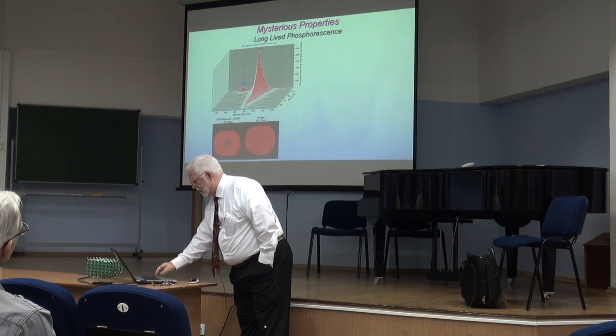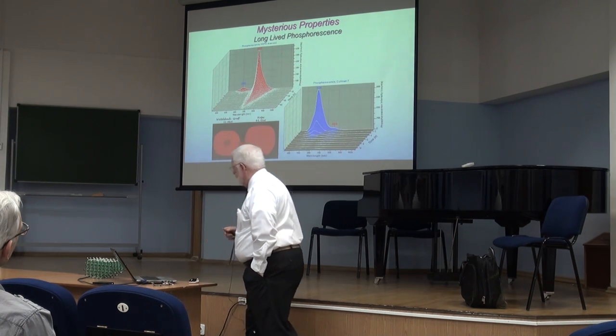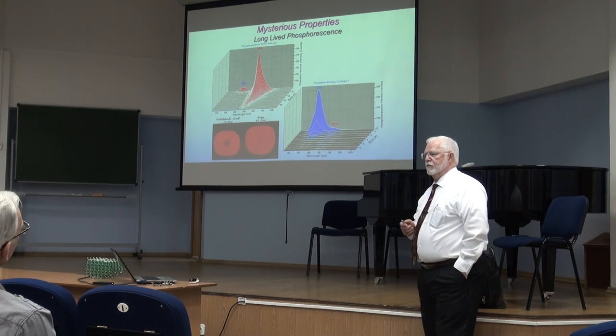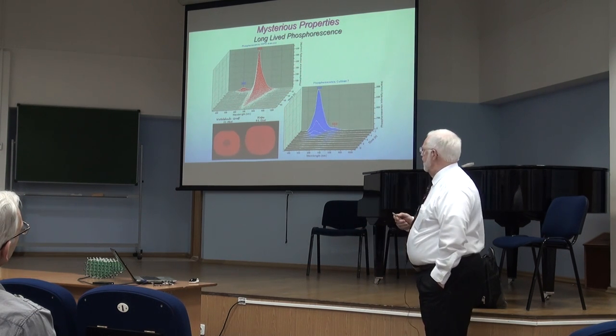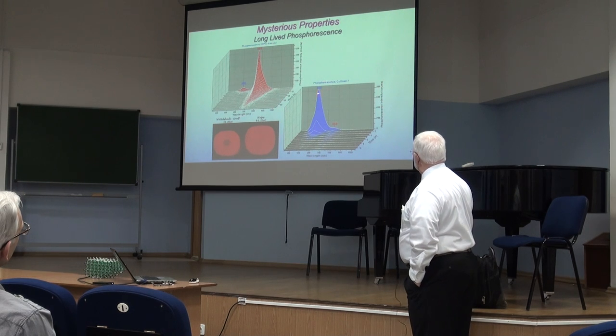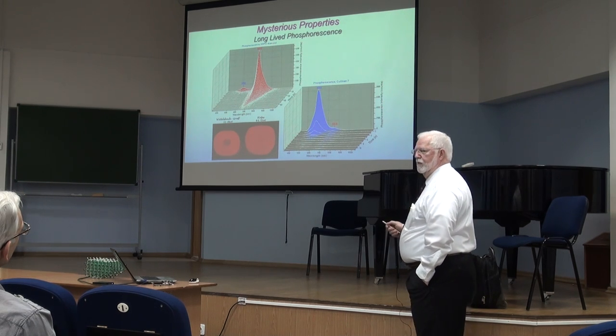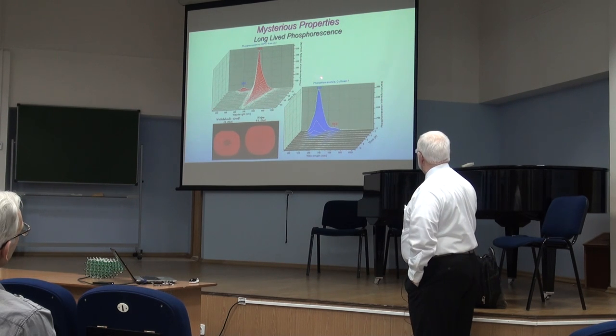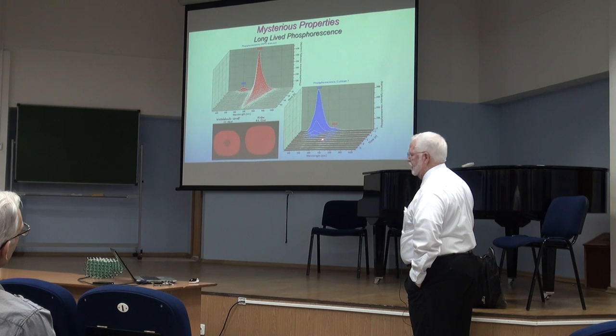Before I comment on that, let me show you another diamond. This is a blue diamond. In fact, we've now looked at about 120 natural blue diamonds, and I would say over 100 of them look like this. They don't have the red glow. They actually have a blue-green glow, so this is generally the stronger band. But you can see that the 660 band is also present in this diamond.